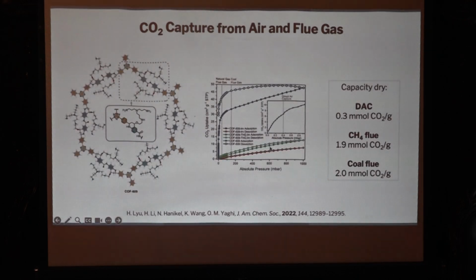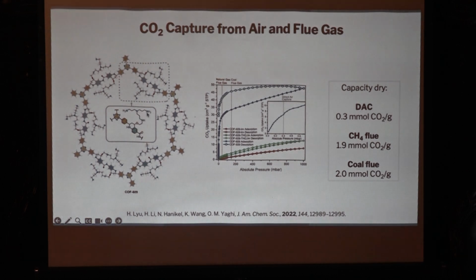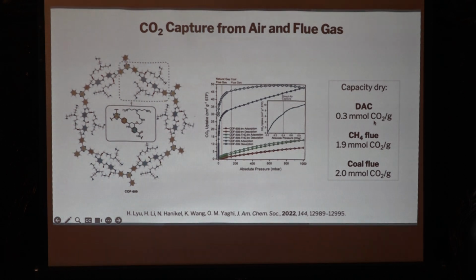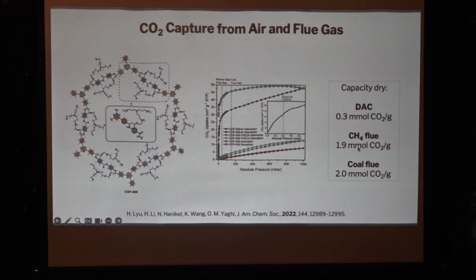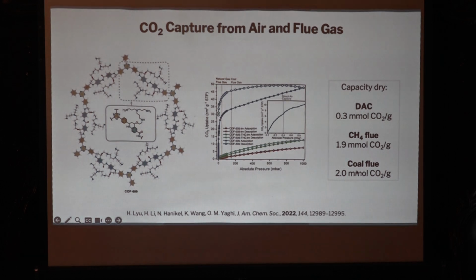And so now we take onto that material, we can put the amine units and look at how much it's taking up. And from the first experiment we did, the direct air capture of CO2 is 0.3 millimole of CO2 per gram. That's dry without water. With water, this number doubles to 0.6 millimole per gram, and so we need to go to 1. But already for methane flue gas and coal flue gas, we're already in the commercialization stage. So are we able to bind CO2 from air using these materials? Yes. Okay. Are we able to achieve the capacity? Yes. And we're almost there with the CO2 capture.